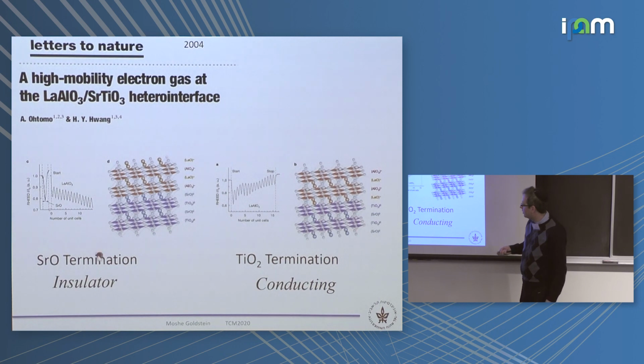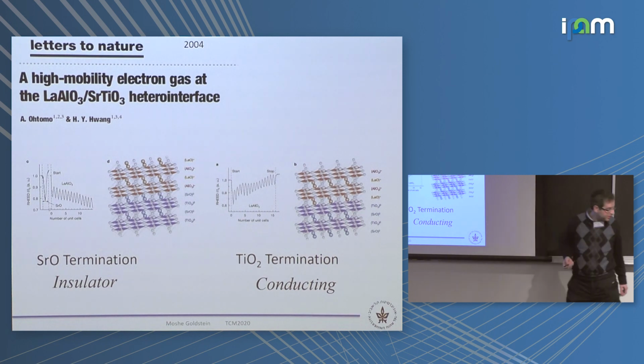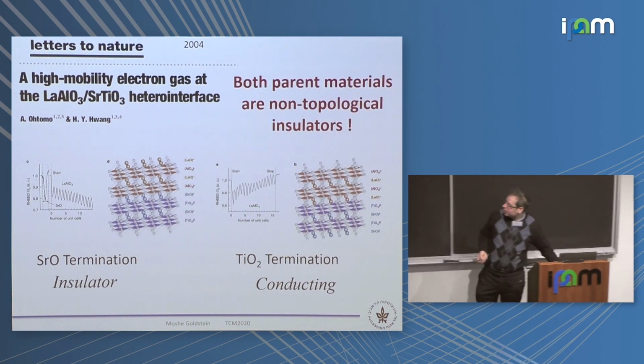that when you do this growth, the STO is composed of titanium O2 layers and strontium O layers. So if it's terminated by strontium O, and then you grow the lanthanum aluminate on top of it, you grow an insulator on top of an insulator. You need to be careful not to dope the material, but you can do that while growing. So you grow an insulator, and it keeps insulating. But somehow, if it's titanium O2 terminated, then you grow an insulator on an insulator, and it starts becoming conducting.